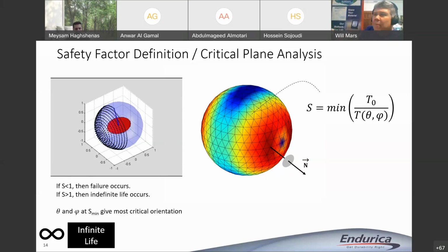And we do it for all the elements in a model, and that tells you whether your part is going to pass or fail that particular set of conditions, right? So this is just the critical plane search, scanning through different possible crack orientations. Once you've done that search, you can visualize the results as colors on a sphere.